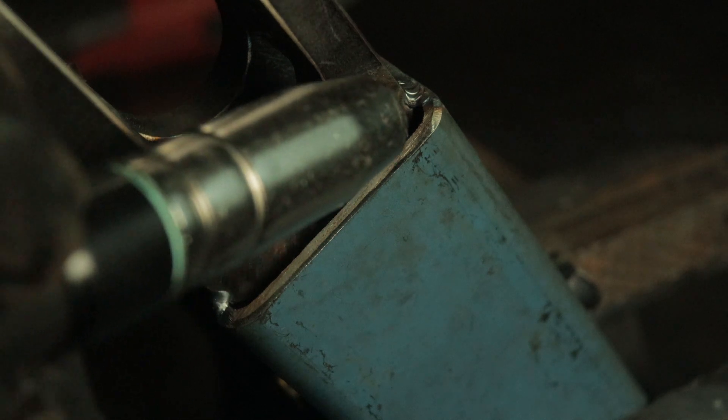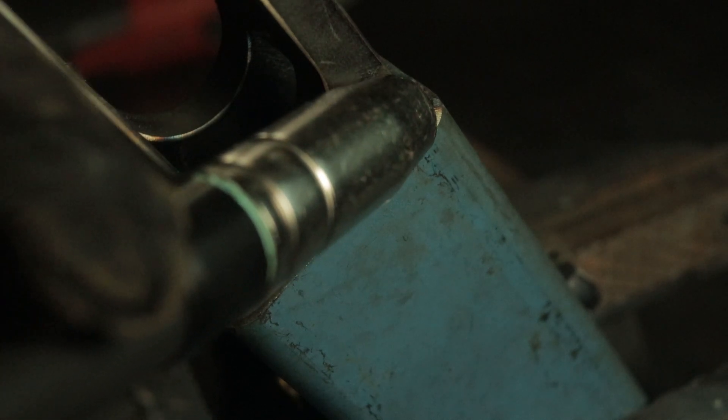For the clamp on the welding stand I had a one-eighth or three millimeter gap between the three-eighth ten millimeter plate and the square tube, so I had the machine set low at 23 volts and the wire speed was at nine meters per minute. The slight downhill position reduced the gravity affecting the weld from falling away.